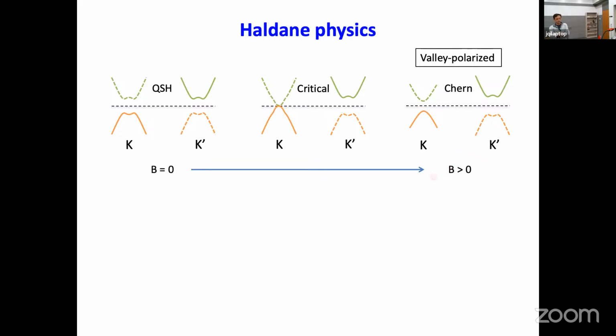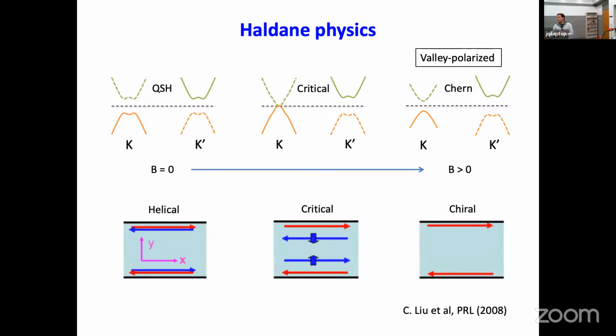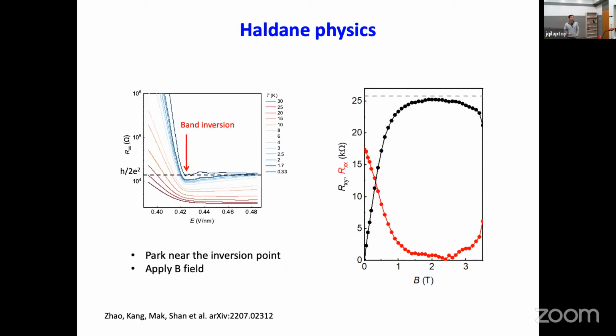So in the real space picture, what's happening is that if you apply this magnetic field, you start with a pair of helical edge states for the quantum spin Hall insulator. Then near this critical point, one copy of the helical edge state gets pushed into the bulk. And after the reopening of the gap, we just have a chiral edge state left, the chiral copy left in the system, and it's a Chern insulator after this. Okay. So this is the data.